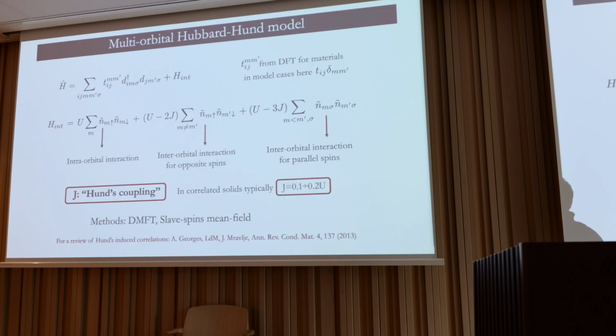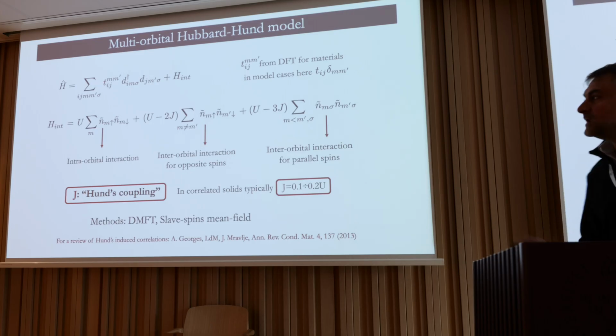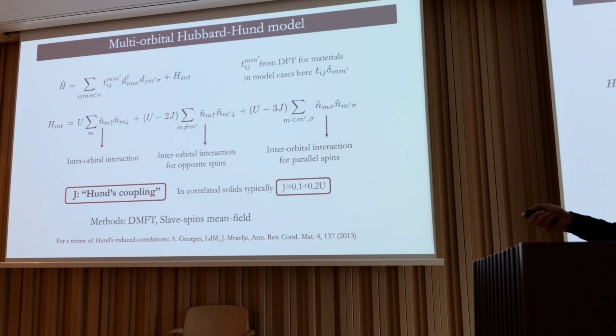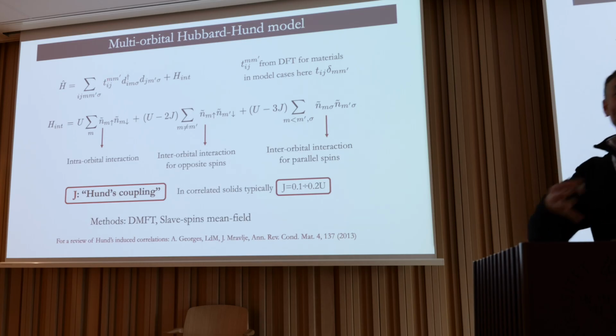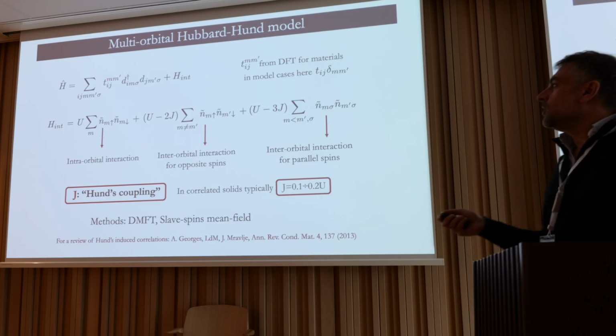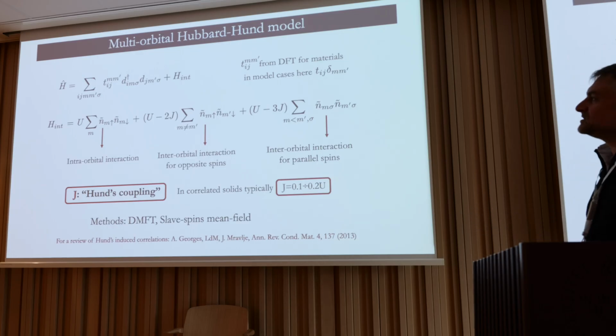So how do we do this? Well, we take a DFT calculation. We do a tight binding parameterization, so where this t ij m m prime between the 3d orbitals of iron are all estimated by ab initio, and then we add the interaction.